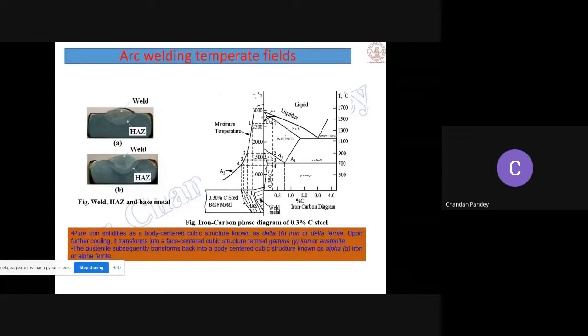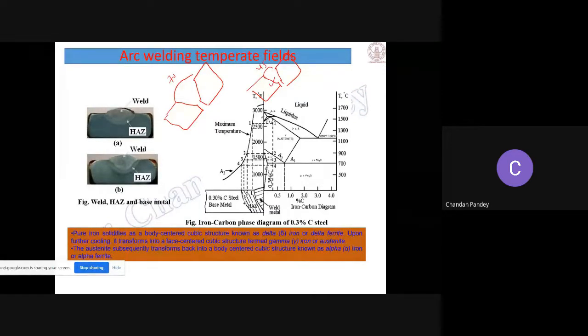Generally, suppose I want to join two plates of different groove geometry. One has a groove angle of 70 degrees, and the second one is a narrow one, about 40 or 45 degrees. In the second case you will get less metal deposition, so the overall heat input will be less and the overall magnitude of the residual stress will be less. So in one case there is 70 degrees and in the second 45 degrees, so we need less filler metal, the cost required will also be less, and the overall residual stress and distortion will also be less.